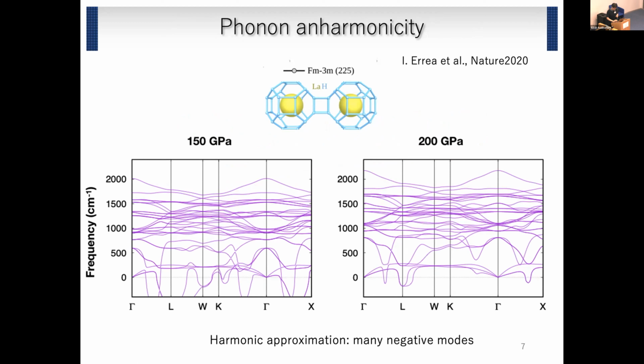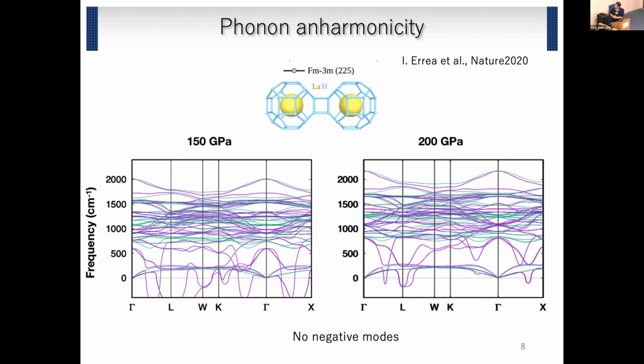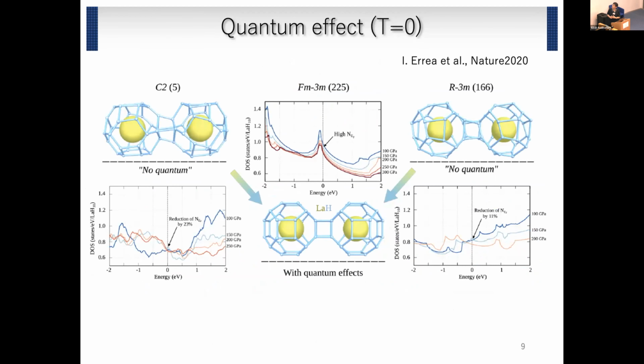And so then in this paper, we also considered the effect of anharmonicity based on the self-consistent phonon theory, SCPT. And then the system becomes dynamically stable. Based on this calculation, if we consider the effect of zero-point motion, we can show that this high symmetric structure, which is good for superconductivity, can be stable even at 150 gigapascal, due to the quantum effect. So this is the calculation for zero temperature.